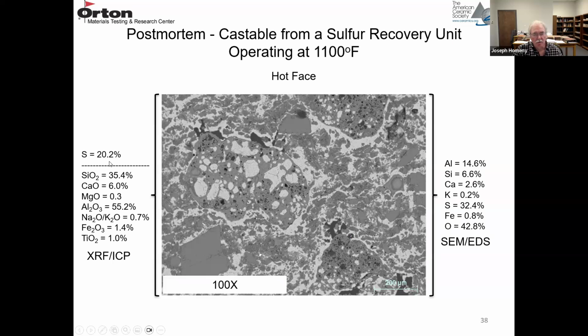There's about 20% sulfur. So you see silica, CaO, and Al2O3. So you see the calcium aluminate cement bonding the alumina silica aggregates. And the SEM EDS analysis of this particular photograph shows alumina, silica, and lime, and oxygen because these are in oxide form, and then the high level of sulfur. Everything that's in the brightest white color here is going to be the sulfur. It diffuses even into the pores of the coarser aggregates and in through the matrix.